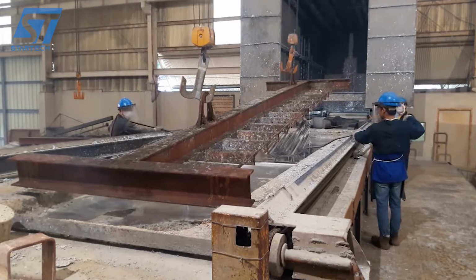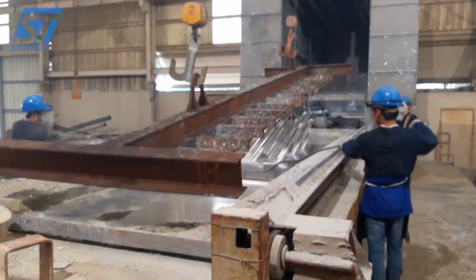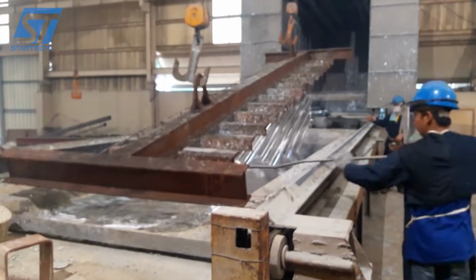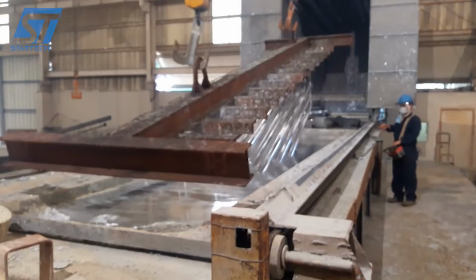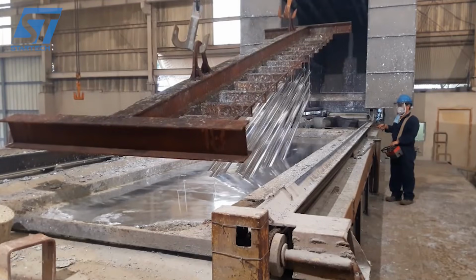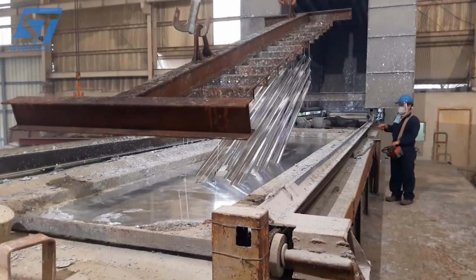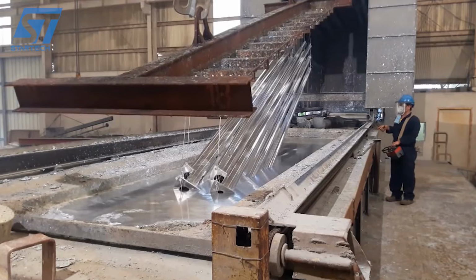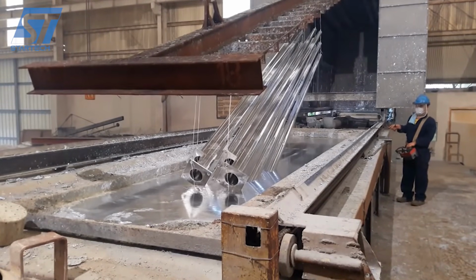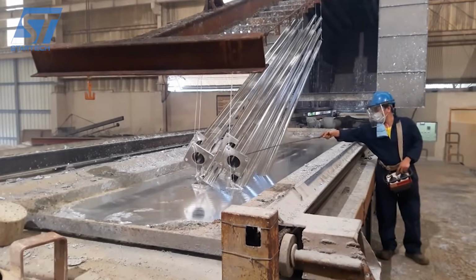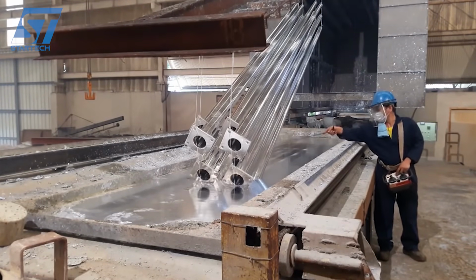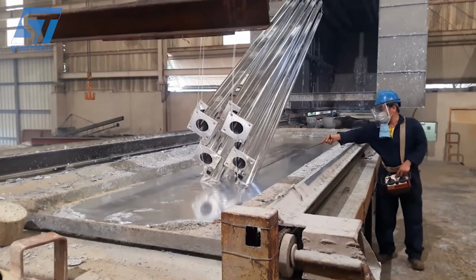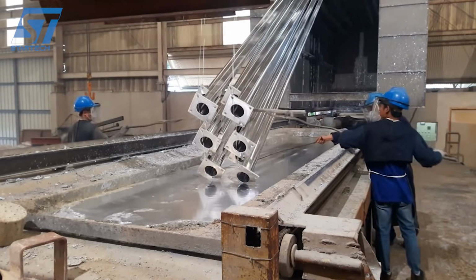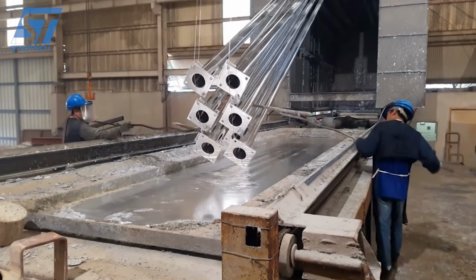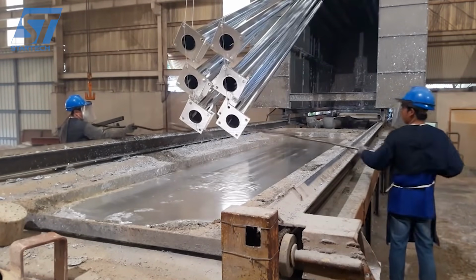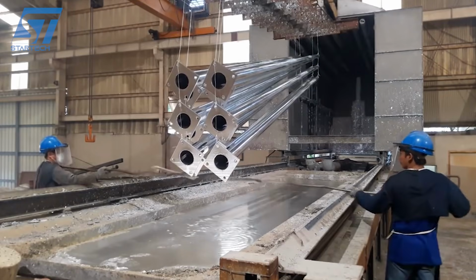Now comes the moment you've been waiting for. The prepared steel is lowered into a bath of molten zinc, heated to approximately 840 degrees Fahrenheit, 450 degrees Celsius. And this is where the real magic happens. The formation of the zinc coating on the steel surface is actually a metallurgical bonding process between iron and zinc during this hot dip immersion. As a result, a zinc-iron alloy layer forms that protects the steel from corrosion. That's not just a coating sitting on top of the steel, it's fused with it at a molecular level. You've got multiple alloy sublayers, gamma, delta, zeta, each with a progressively higher zinc content as you move from the steel outward to the pure zinc outer layer.